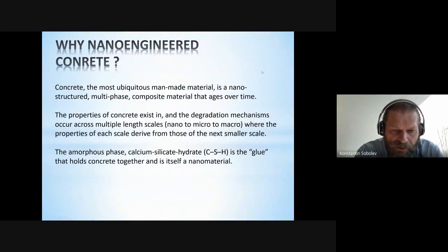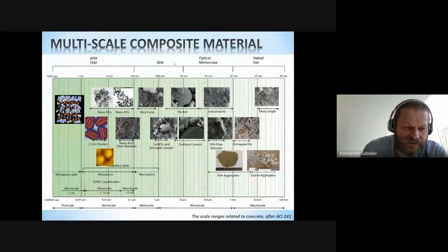If we look at concrete, we understand that properties and degradation mechanisms occur across multiple length scales. As small as we can now detect is nanoscale, and the properties at macro scale can be manipulated by improvements at nanoscale. For example, calcium silicate hydrate, the main building block of hardened cement paste, is a nanomaterial at nanoscale, and this can be detected. First we had artist renderings of the CSH clusters, and later we were able to see it with atomic force microscopy.